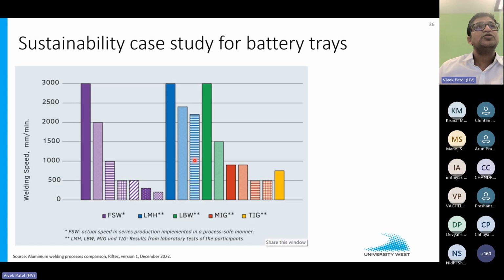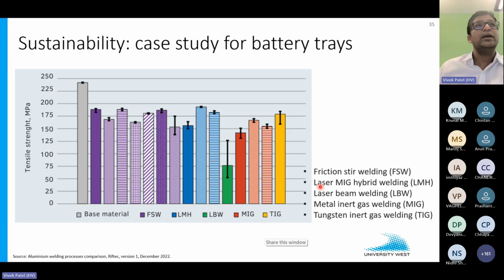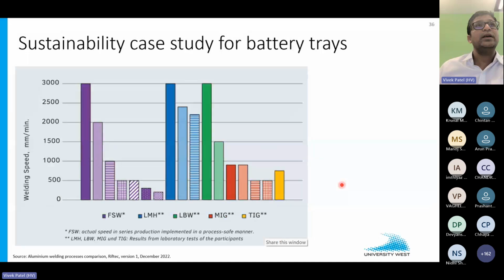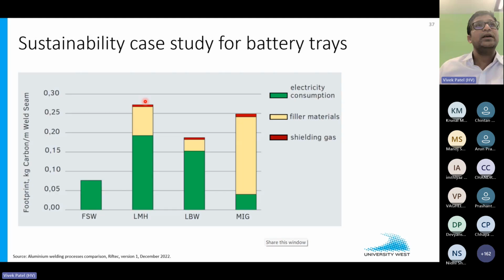Then we also tried to understand the welding speed from a sustainability perspective. So how far you can push, up to 3 meters per minute was a target, and you can see this laser beam welding, obviously, and some of the laser MIG hybrid welding. So this LMH is nothing but a combination of laser source and MIG source to make it high speed. So these three processes were competing with each other in terms of tensile strength and welding speed. But then after